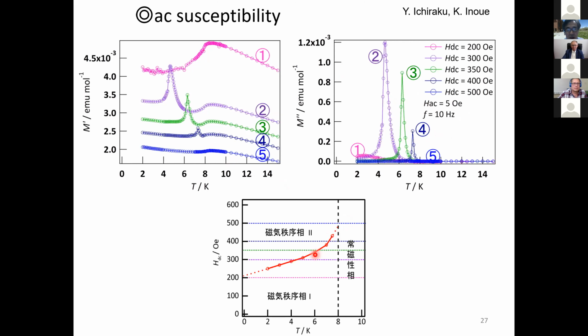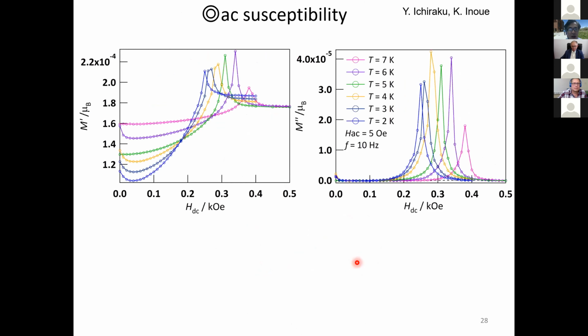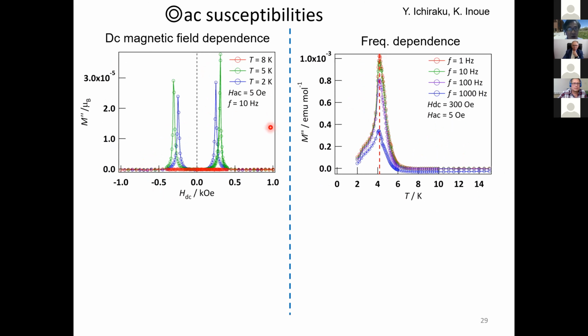You can put the phase on the phase diagram. The line is coming like this. Here is magnetic phase 1. This is magnetic phase 2, and here is the paramagnetic phase. This is the field dependence of AC magnetization. If we change the field at an isothermal temperature, you can find anomalies below TN. Yes, here is also similar.